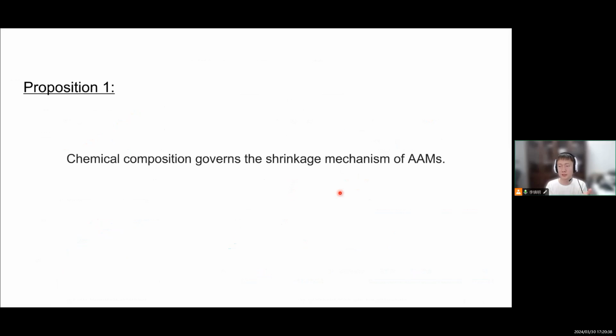For example, in Portland cement, the pozzolanic reaction is caused by the reaction of CH. CH is also alkali. So why is that not alkali activation? Actually, the name doesn't matter. AAS is more similar to Portland cement than to the fly ash or metakaolin systems. Fly ash is a waste, but metakaolin is a resource. But these two systems are more similar to each other. And AAS and Portland cement, these two are more similar. So we should look at the chemical composition. That is what I want to say here.